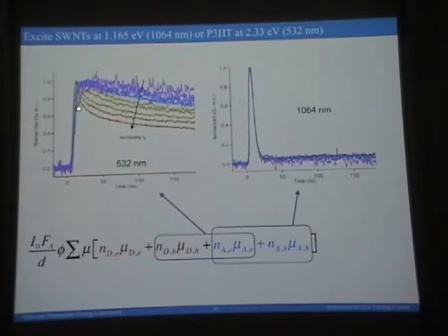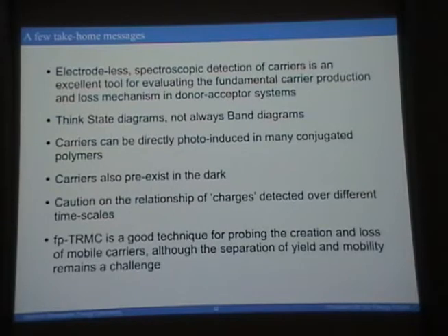If you put the nanotubes in a blend of the polymer, you can see we get transients again. This is kind of nice. These transients you see here are now the electrons in the carbon nanotube, which is perfect. In fact, we even see the electrons banging off the end of the nanotubes, even if they're a micron long, which is rather nice. But this shows that the carbon nanotube can act as an acceptor. It's always assumed that it will do that. Rarely is it shown.